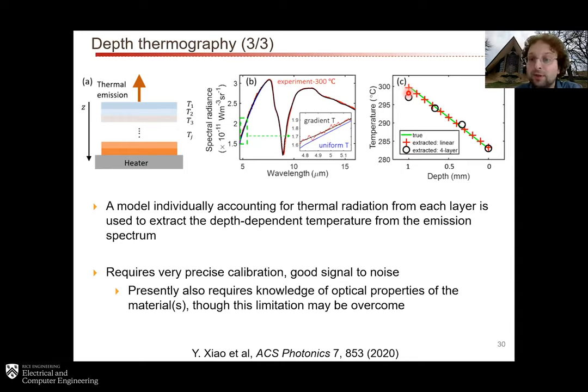It's a little bit lower. This is all the way at the bottom. At the bottom, we have a temperature that's almost 300, which is what you would expect because that's the heater temperature. But when you get to the surface at a depth of zero, you have a temperature that's in this case about 282, 283 degrees Celsius because, of course, there's a thermal conduction through the surface and the air is colder than the heater underneath. And so these are the results of this retrieval. So the green line is what we assume to be true based on straightforward calculations with thermal conductivity. And then the symbols are our extraction algorithm.